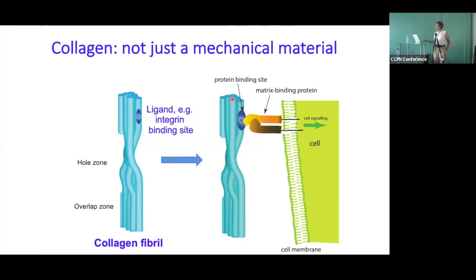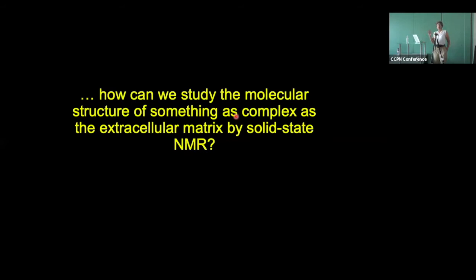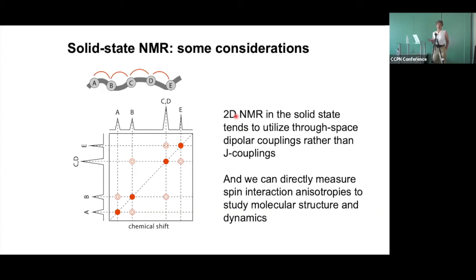It's really the structure of these binding sites, their accessibility and dynamics, that we need to investigate by solid-state NMR. How can you study something as complicated as a whole tissue by solid-state NMR? In exactly the same way you study highly complicated molecules in solution-state NMR — we need 2D NMR, for structural reasons and to be able to assign the spectrum. We make more use of the dipolar coupling than the J-coupling. Each dimension of the spectrum contains the normal one-dimensional carbon-13 NMR spectrum, representing each carbon site in our biopolymer.